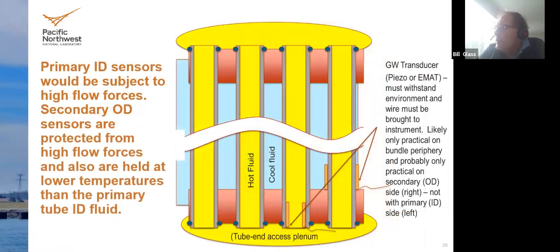So it is possible, and some people have demonstrated that you can put a sensor here at the end of the tube, inside the tube, and send an ultrasonic wave up along this tube. And it travels quite efficiently, and you can see relatively small flaws down to 50% through wall small pits from a sensor mounted inside the tube. You can go into a heat exchanger and do that when the heat exchanger is offline. But if it's online, it's tough to do that.